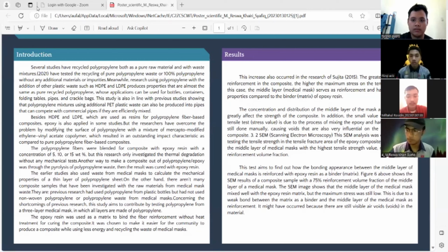This increase also occurred in the research of Sujita 2015. The greater the amount of reinforcement in the composite, the higher the maximum stress on the tensile strength. In this case, the middle layer medical mask serves as reinforcement and has strong tensile properties compared to the binder matrix of epoxy resin. The concentration and distribution of the middle layer of the mesh as reinforcement greatly affect the strength of the composite. In addition, the small value obtained in this tensile test stress value is due to the process of mixing the epoxy and hardener, which is still done manually.